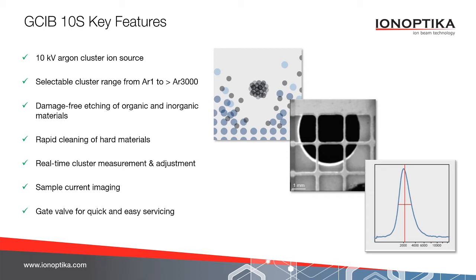Obviously, it provides damage-free etching of organic and inorganic materials. It also is a really valuable means of cleaning a sample, for example, metals, semiconductors, or other hard materials. Two key features of the GCIB 10S are that it provides real-time cluster measurement and adjustment. And I'll go into this in more detail later. We also provide a means of imaging via sample current imaging. And these features are unique to the GCIB 10S. There's also a gate valve for quick and easy servicing so that the analysis chamber is not vented to air if the gas cluster ion beam needs to be serviced, or vice versa. If the chamber is being vented, the column in the ion beam can be maintained at high vacuum.